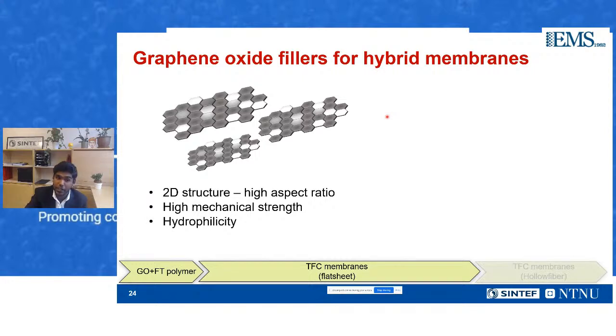The second biggest advantage is that, due to this 2D structure and the carbon backbone, it has very good mechanical strength. We also know that graphene oxide as such has a lot of hydroxyl groups on the surface, which makes it more hydrophilic in nature, which is very compatible with facilitated transport membranes.